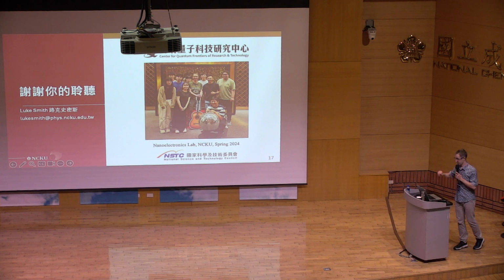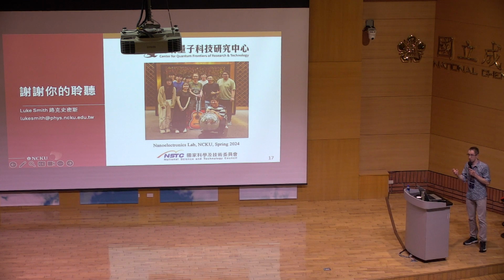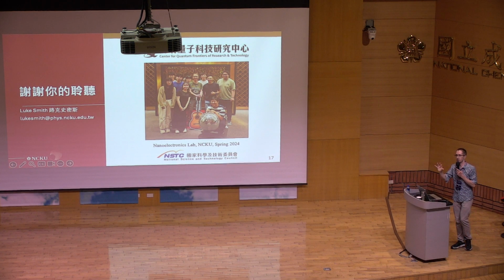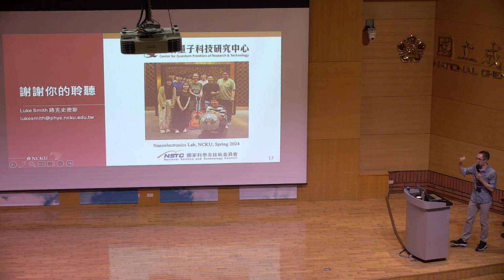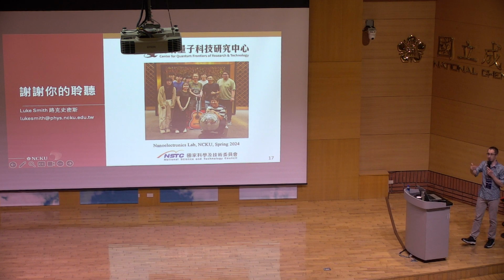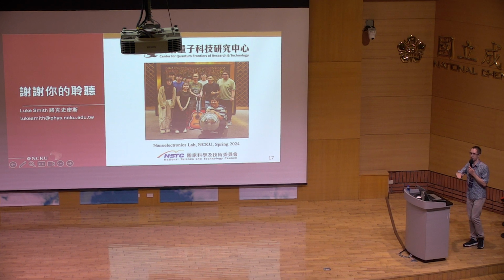I haven't shown the results here, but if you do optical measurements like Raman and photoluminescence spectroscopy, there are some quite clear characteristics, so you can calibrate the thickness of your tungsten diselenide to your Raman or your photoluminescence signal. If you then compare your flake before you oxidize it and afterwards, you'll see that you transition from either 2 to 1 or 1 to 0.